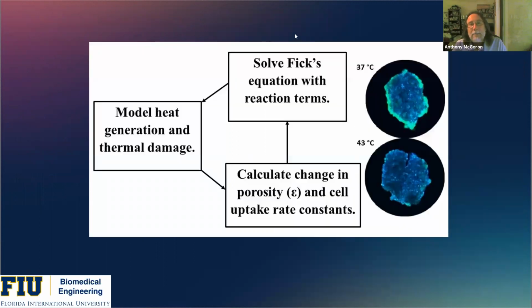So we took the parameters for the interaction of the nanoparticles with the cell and used the Arrhenius model to model the effect of thermal damage on the cells, and predicted its effect on a change in the porosity of the extracellular fluid between the cells in the spheroid. So we modeled the heat generation and thermal damage, and calculated how that could change porosity and cell uptake.